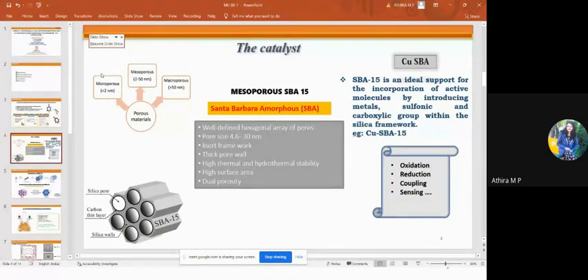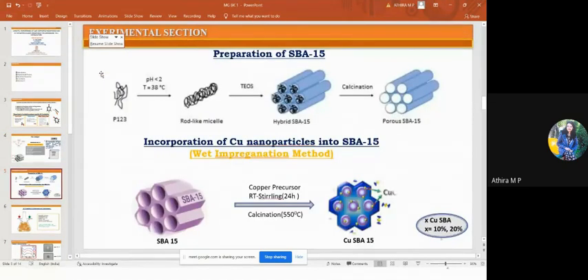Among various silica based systems, SBA-15, that is Santa Barbara Amorphous, has a good pore size between 4 to 30 nanometer, an inert framework, thick pore walls, dual porosity, and high surface area, and has been studied as a good catalytic support since it was developed. This copper modified SBA-15 is an efficient catalyst for several reactions, including oxidation, cross coupling, hydrogenolysis, reduction of dyes, sensing, etc.